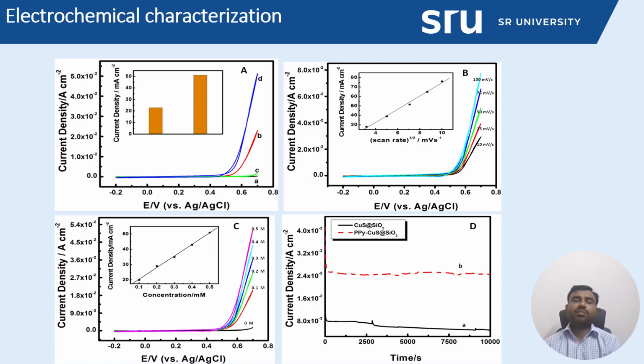This improved oxidation peak current and good stability is mainly due to the coating of conducting polymer over the copper sulfide. As explained previously, the polypyrrole plays two roles. One is that it acts as a protecting layer, so it does not leach out any copper ion, and avoids the intermediate adsorbing during the methanol oxidation. It produces some intermediates, which easily adsorb on the catalytic active sites and block them. Hence the catalytic performance slowly decreases.